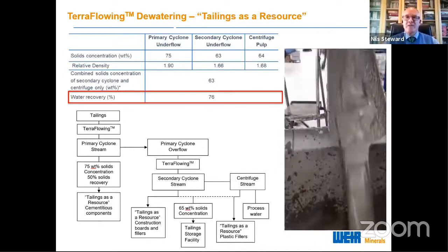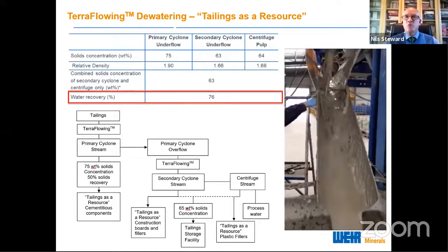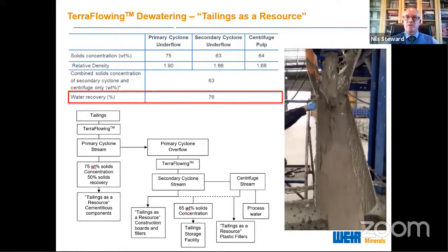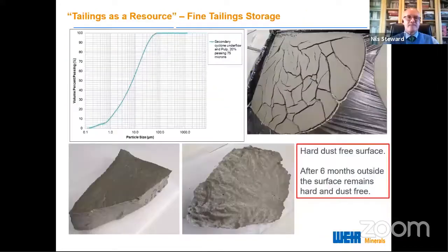So we can take this stream and we can store this within the tailings embankment that we have constructed out of the primary cyclone underflow. Now, there is a benefit that we have seen from doing this, and I need to explain this in a little bit more detail. Here is the particle size distribution of what you're looking at now. So it's 100% below 50 microns. We made a placement inside our warehouse of this product. We measured the yield stress with time, and after about 2 weeks, we were looking at about 600 Pascal yield stress, which means it wasn't flowing anywhere.